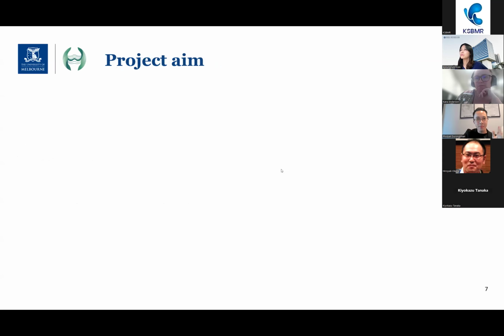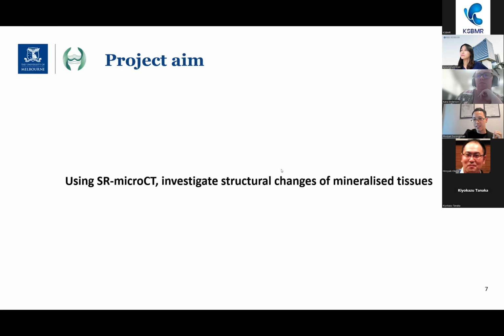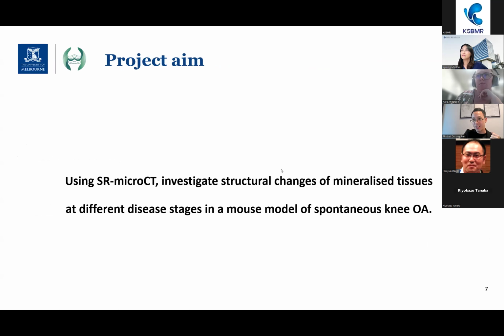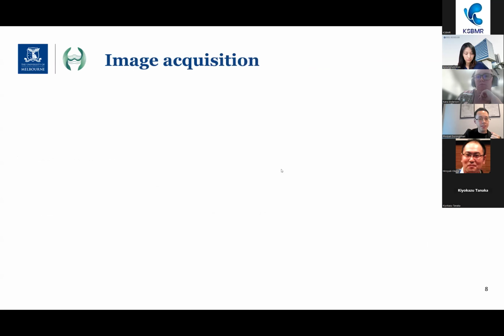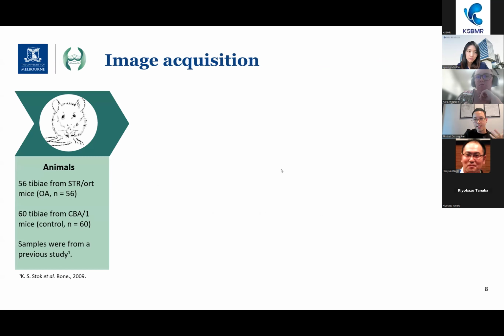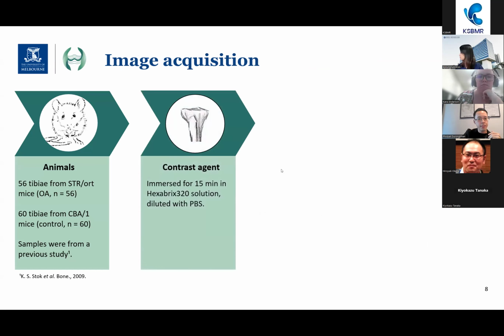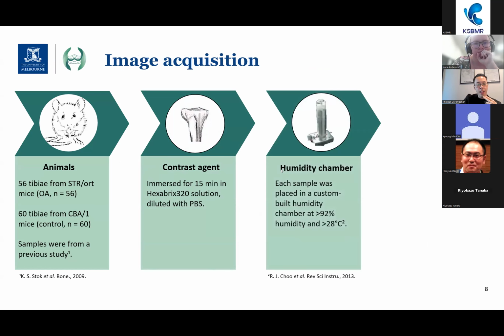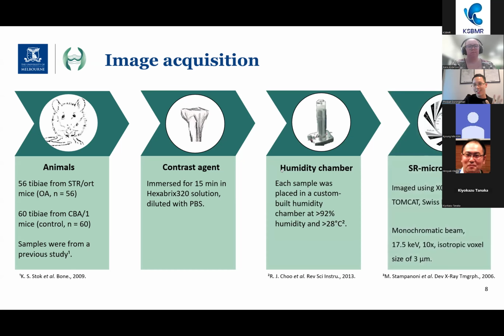So this is going to be a demo study that I ran recently, just to show you what it can do and how to process the images. In terms of this data set, we have a mouse model of OA. These are spontaneous models, so they have to grow really old. Then we dunk them in contrast agents because we also want to see cartilage, so we can quantify the remodeling activity together. Then we place them in a humidity chamber to keep the cartilage humid, otherwise it's going to dry out during the imaging process. And then we chuck them into this high